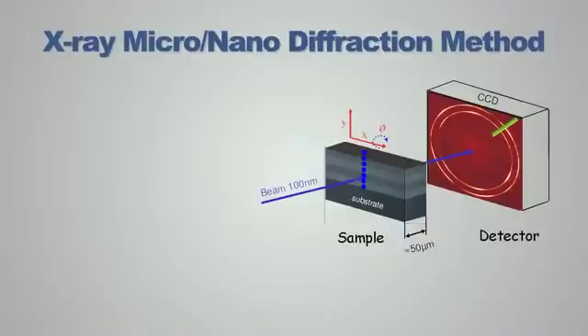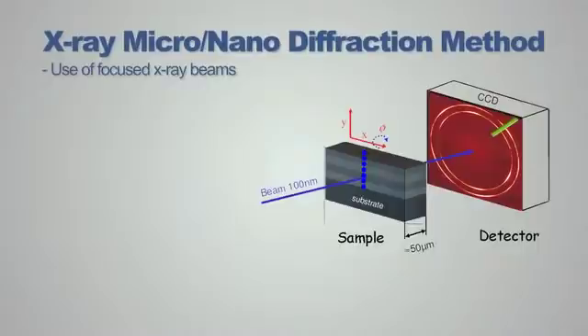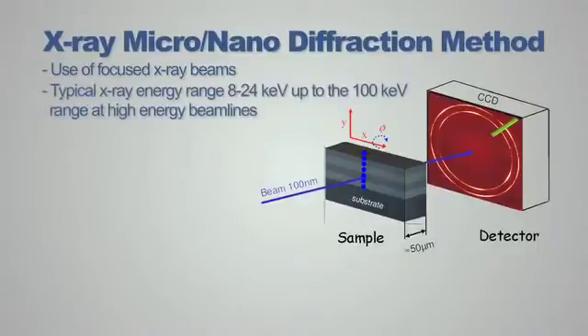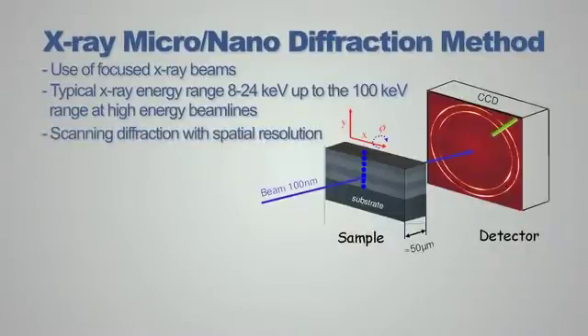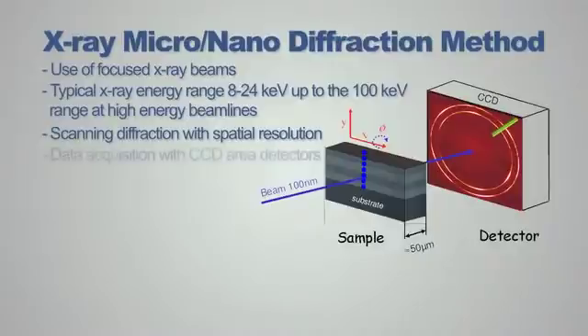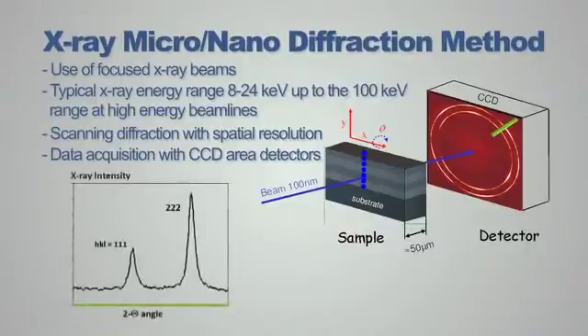On this image you can see a sketch of the functional arrangement of the micro diffraction setup. The micro diffraction technique is based on a very small, highly focused beam — 100 nanometers to the order of microns. You use a heterogeneous sample, such as this layered structure, which can be exposed at different positions by a high resolution scanning device to the beam. Like this you can record diffraction images one after the other with a CCD detector and examine the diffraction patterns, as you can see for example at the left on this view graph showing two diffraction peaks.